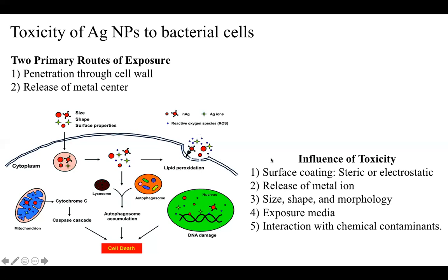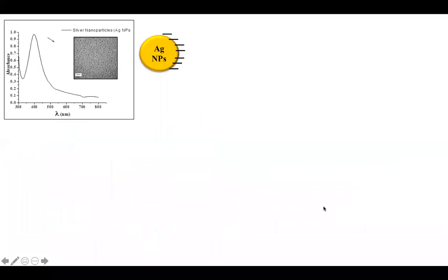And this is influenced by 5 primary factors. 1, surface coating, whether it's steric or electrostatic. In our case, we're looking at electrostatic because we have the citrate coating and we have these heavy metals with a positive charge. The release of the metal ion, which is why we're comparing silver nanoparticles and silver ions; the size and shape and morphology; the exposure media; and the interaction with chemical contaminants.